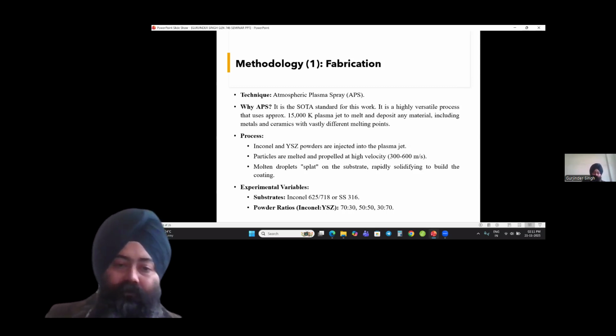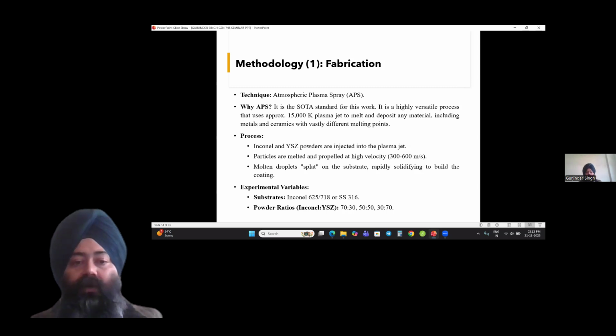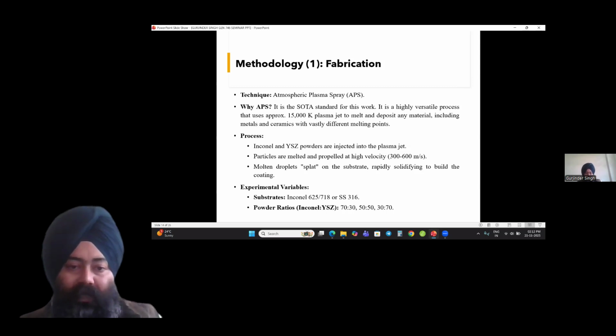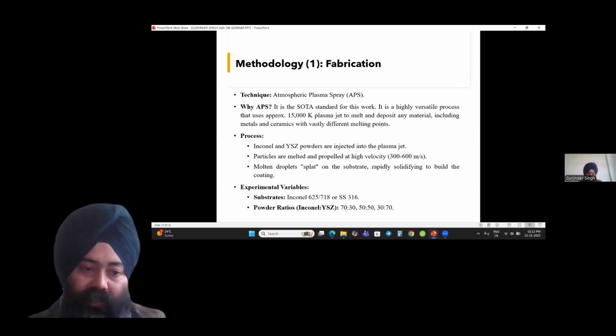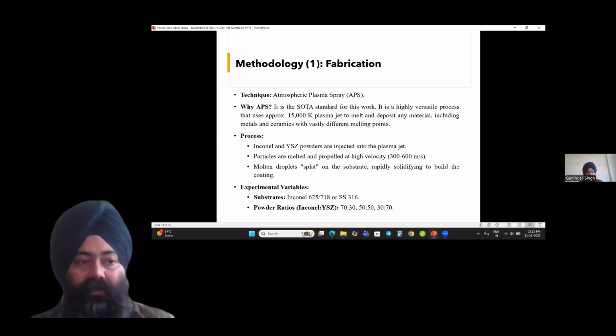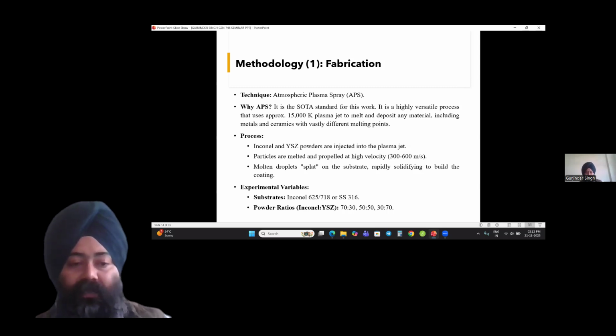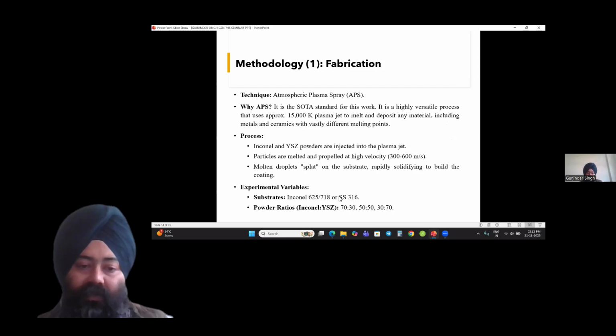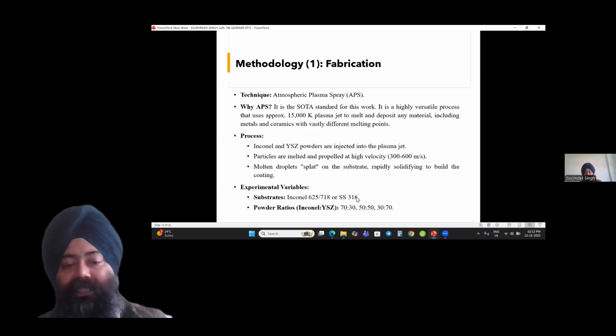After being propelled, the molten droplets splat on the substrate, rapidly solidifying to build the coating, which results in the complete coating. So what are the experimental variables? Substrates are Inconel 625, 718 or SS316, that is stainless steel. And what are the powder ratios? Again, as discussed earlier, 70:30, 50:50, and 30:70.